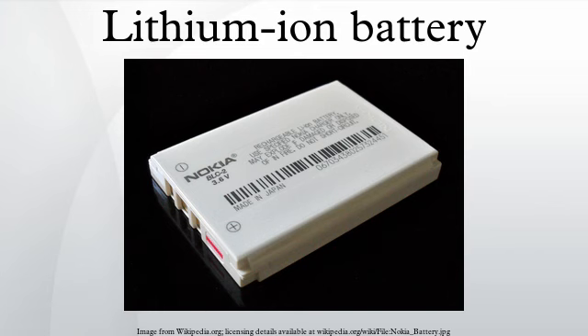Batteries with a lithium iron phosphate positive and graphite negative electrodes have a nominal open circuit voltage of 3.2 V and a typical charging voltage of 3.6 V. Lithium nickel manganese cobalt oxide positives with graphite negatives have a 3.7 V nominal voltage with a 4.2 V maximum while charging. The charging procedure is performed at constant voltage with current limiting circuitry. Typically, the charge is terminated at 3% of the initial charge current.